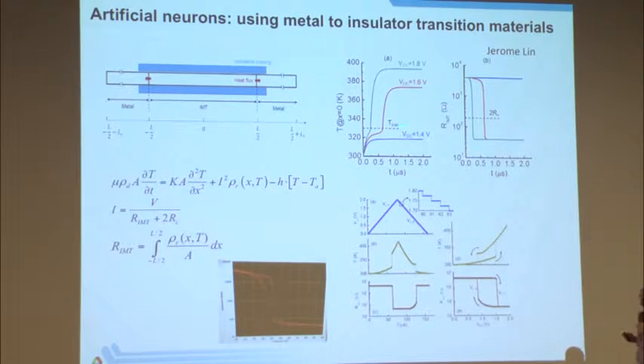And in the graphs over here, I will ask you to just focus on the one on the right. When you fire it under certain conditions, we see that it will change its resistive state. If you do what's called a quasi-static simulation, where you increase its voltage slowly in steps and then back down again, you will get a hysteresis in its turn on and its turn off. And the hysteresis simply comes about because it has two different states in resistance from when it's heating up to after it's heated up, and the power dissipation is then different because the power is V squared over R. And R is different in this arm and this arm. So there's a lot of interesting, rich phenomena here that can be used in a compact device model if you look at it from a purely electrical engineering point of view. And this is what Jerome is trying to do.